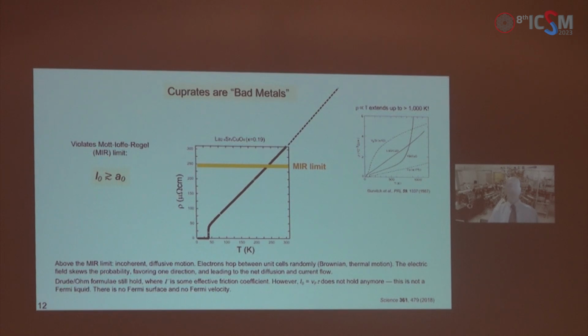When you compare this to 10 Kelvin, that's 100 times more. So the ratio of the T to the fifth term versus the T-linear term should have grown by 8 orders of magnitude. But we don't see any of that. Moreover, the Ioffe-Regel limit is exceeded actually by a large margin. And that's why cuprates are called bad metals. This is called the bad metal behavior, meaning that the Ioffe-Regel limit is exceeded.